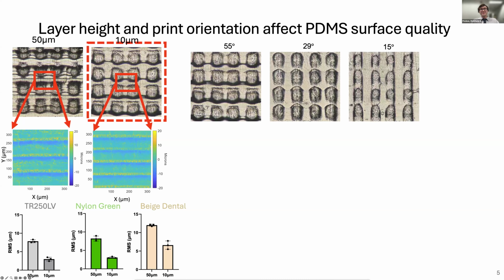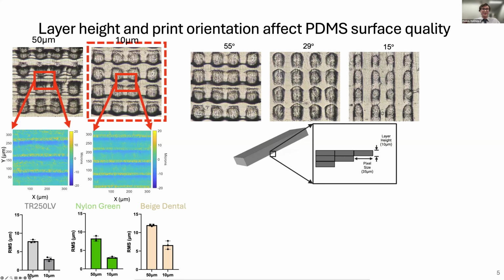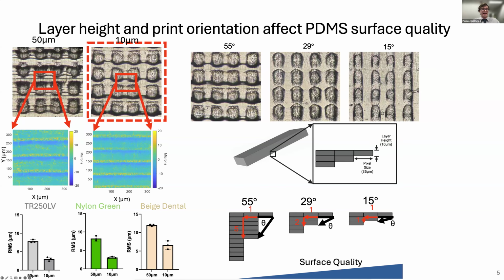We next wanted to investigate how different printing orientations affect the quality of the PDMS. We looked at 3 different orientations: a 55-degree angle from the x-axis, 29 degrees, and 15 degrees. This angle matters because whenever you angle the part, the surface is discretized into voxels, an effect known as aliasing. Depending on how the part is angled, you have different extents of aliasing. At 55 degrees, you'd be going over 1 voxel and down 5, and at the other end, going over 1 and down 1 at 15 degrees. Because you have less aliasing at 15 degrees, you should, in theory, have a smoother surface and a higher surface quality.